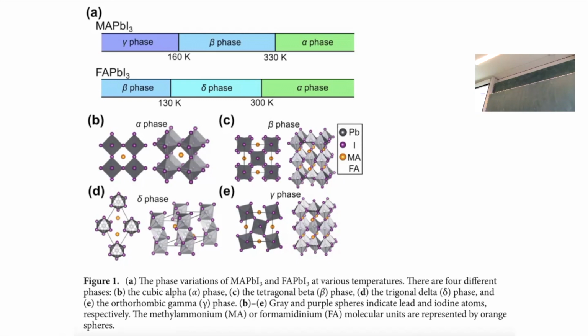The alpha phase is depicted here. It's a very nice cubic packing. All the components are exactly in a cubic lattice, as you hope, like ideal. There are these octahedra, formed by the halogen. And in the delta phase, the yellow phase here, if you look at the sides, you see that the connection between these octahedra is lost. So it is as if these octahedra move in the crystal, and thereby the conjugation is lost. So there's no more interaction with the next layer. That makes it yellow. So this is the yellow delta phase, and we want the black alpha phase.